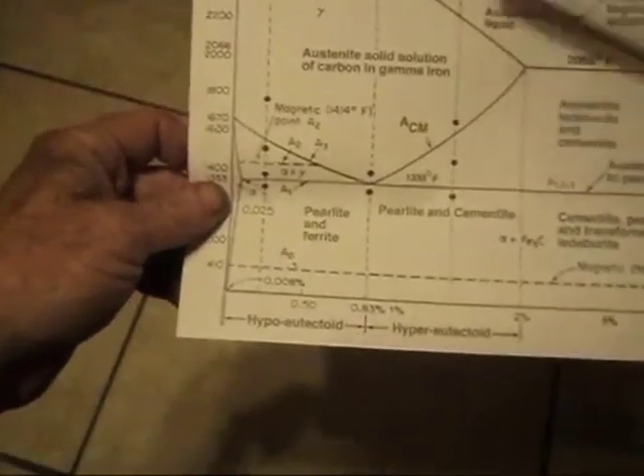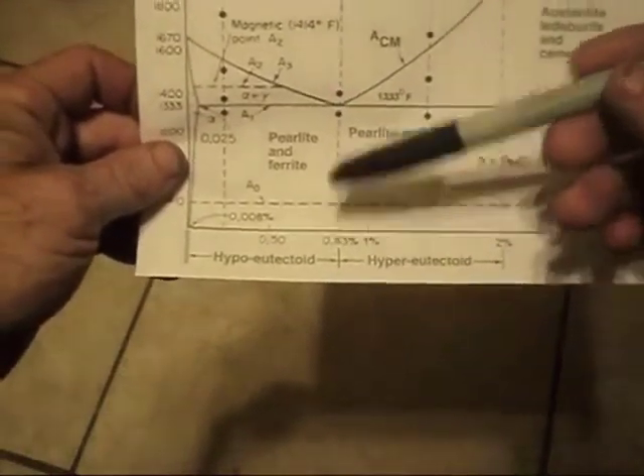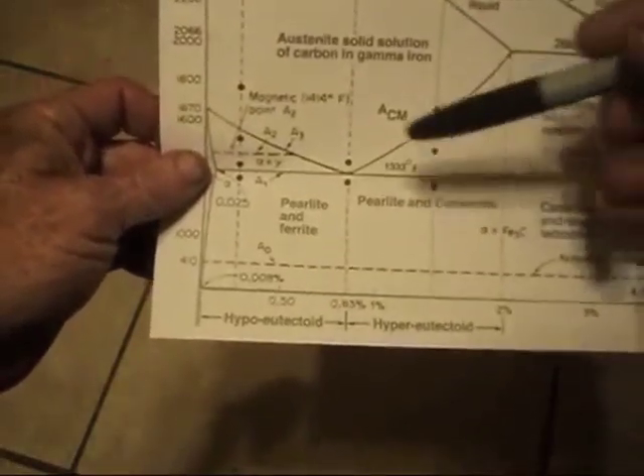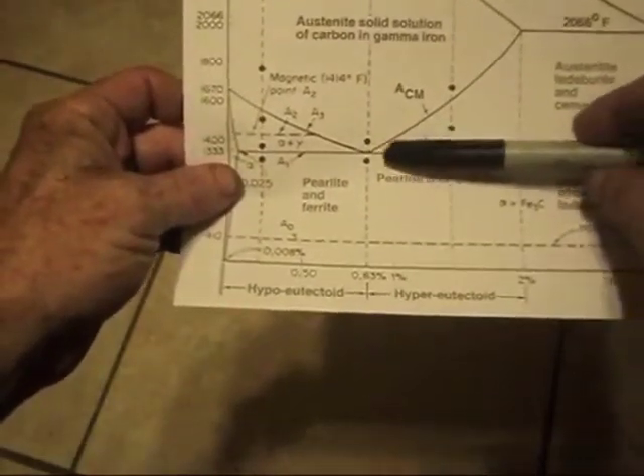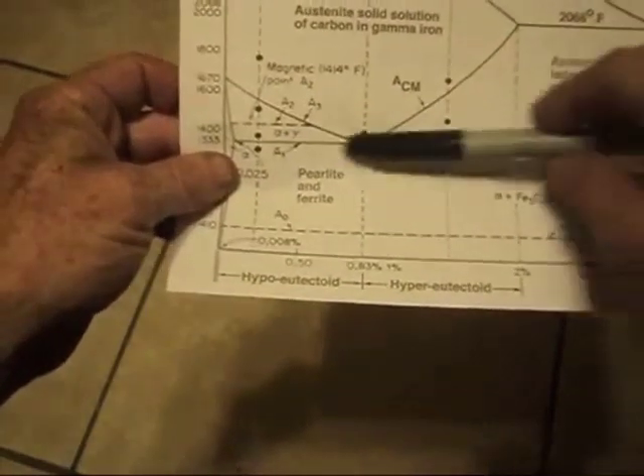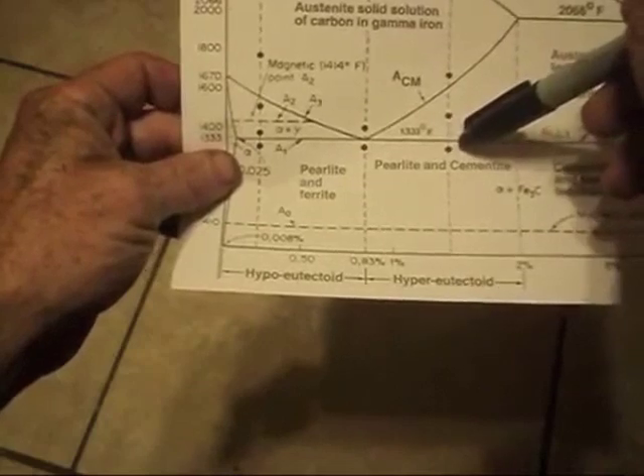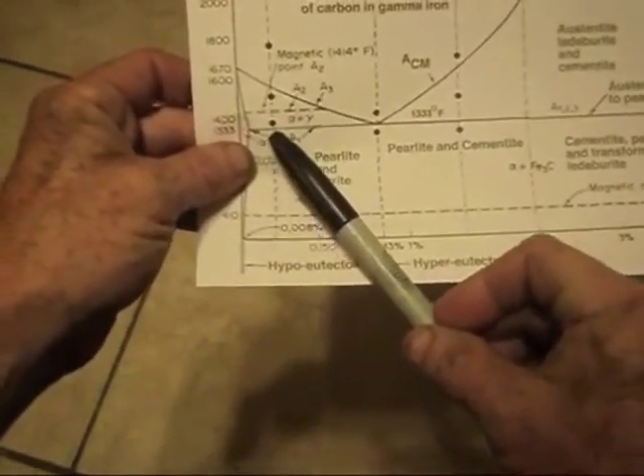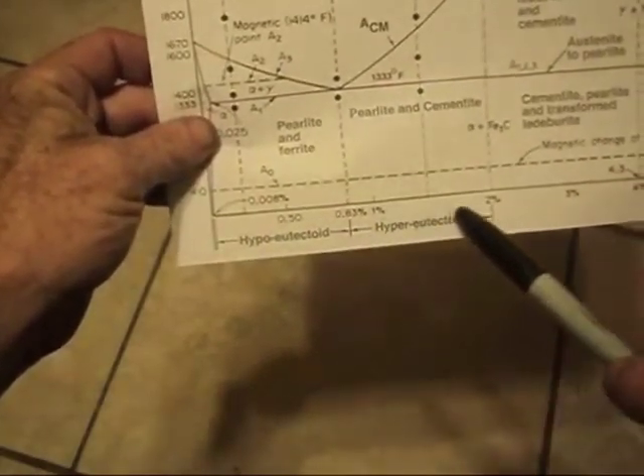This is an iron carbon phase diagram. It has your temperatures over here and your carbon content down here. Everything past this line is cast iron. Anything over 2% carbon is cast iron. Right here in the very center, you have the eutectoid line, which is 0.83 to 0.84% carbon. 1084 is eutectoid steel, which means that this line is the lower transformation temperature. This is where your steel is going to lose its magnetism. And you'll notice that this line does not change at all for the amount of carbon in the steel.